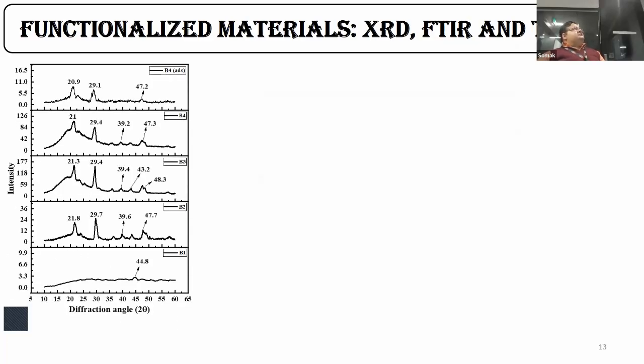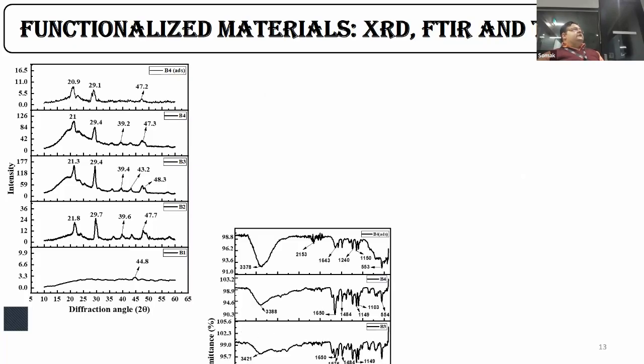Next, we came across XRD analysis, and we were able to see the sulfone groups, the pyrrole groups, and the aniline groups, mainly observed through various peaks. The main one here is at 47 degrees, which corresponds to the aniline group in polypyrrole, also the aniline group in polyaniline, and the pyrrole groups mainly represented at 29 degrees.